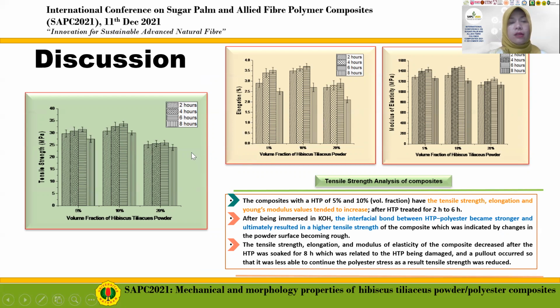As you can see in the chart, we have found that the composite with a powder of 5% and 10% volume fraction has tensile strength, elongation, and Young's modulus values that tended to increase after the powder was treated for 2 hours, 4 hours, and 6 hours. From this chart, we know that after immersion in potassium hydroxide, the interfacial bond between powder and polyester becomes stronger and ultimately results in a higher tensile strength of the composite, which was indicated by the change in the powder surface becoming rough.